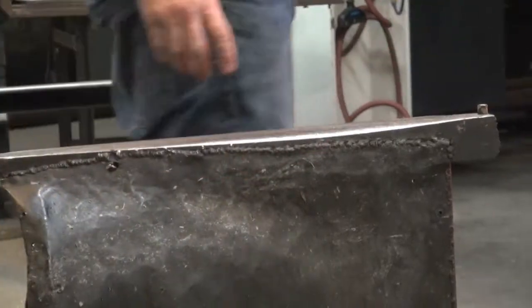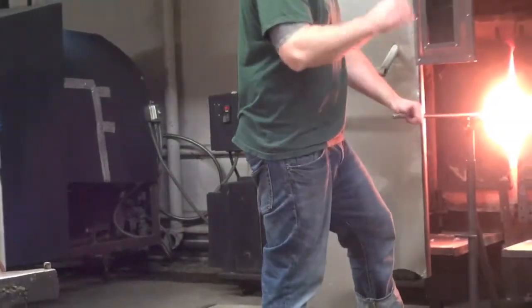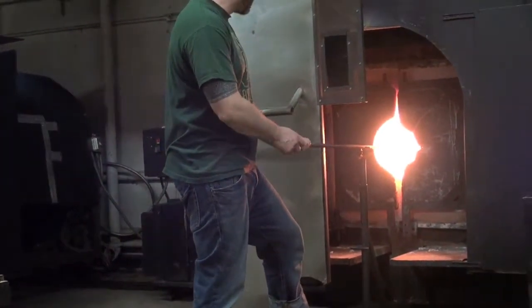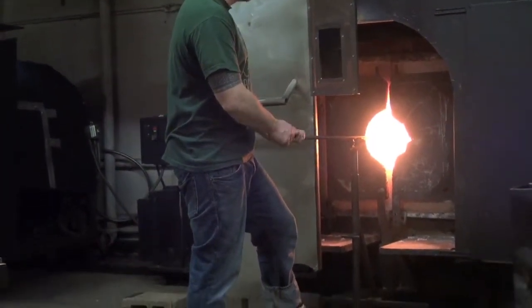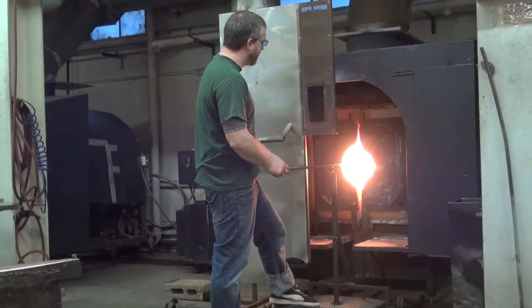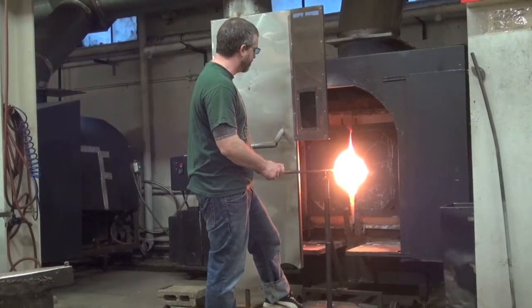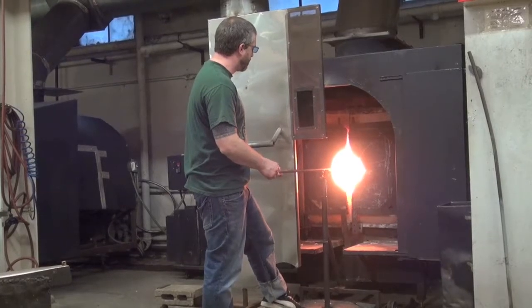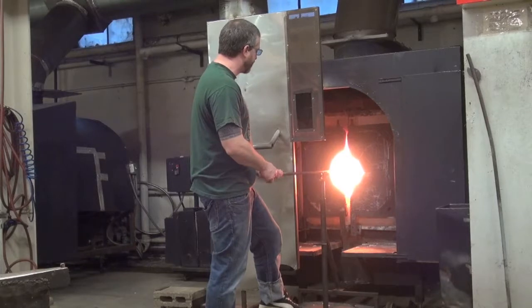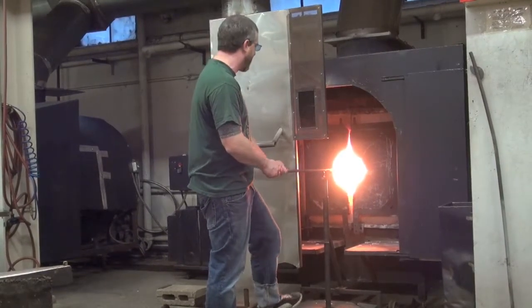I want to go ahead and take another heat on this. I want to make sure that I've got a really nice clean line, because if I have a divot there, when I gather, that divot's going to probably trap a little air pocket or a little air bubble. But also, it might be hot enough that the color is moving some, but it might not be so hot that the core is fluid all the way through. And if I were to blow into it, but the core might be a little cool at one point, it's obviously going to push the other direction, and therefore my bubble is going to be off center, which is going to make gathering over it a little bit more troublesome. It also makes doing the overlay of it, pulling that back, a little more troublesome.